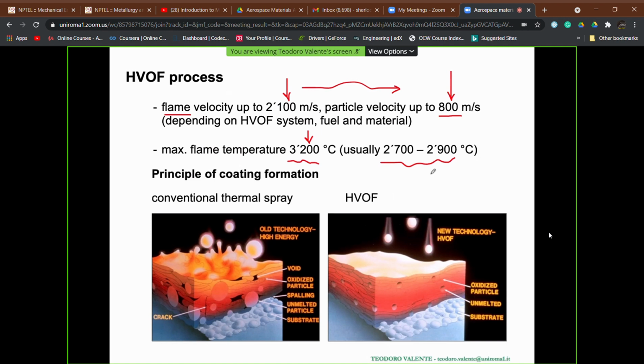Some examples of coatings made by ceramic materials using HVOF have been done. But in this case, we need a very strict control on the average size of the particles, which must be of the order of 10-15 micrometers, with respect to the standard for the HVOF, which is around 20-25, sometimes 30, because by reducing the diameter of the particles, we could expect, and this has been proved, a sufficient degree of melting of the particles. But in any case, the most used technology in this case is plasma.